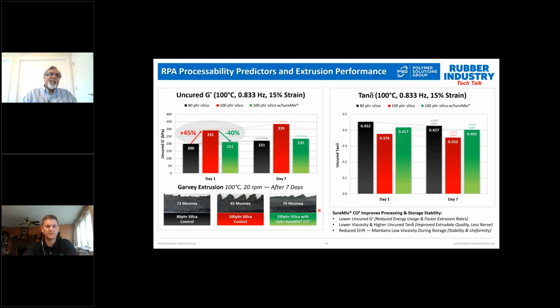Thank you, Ricky. Right, so you can see in this compound, increasing the silica loading from 80 to 100 parts. For those who've either done that or tried to do it, one thing that you'll know is that it's very difficult from a processing standpoint, but the performance gain is incredible. So going from 80 to 100 parts of silica, the wet traction improvement is very substantial. So this is something that everybody would like to be able to do in a tire tread, but it's extremely difficult in a manufacturing environment.